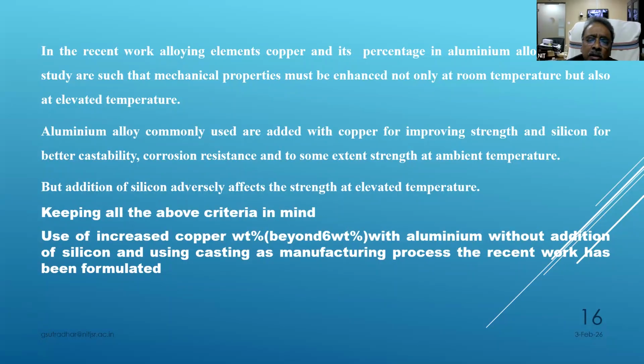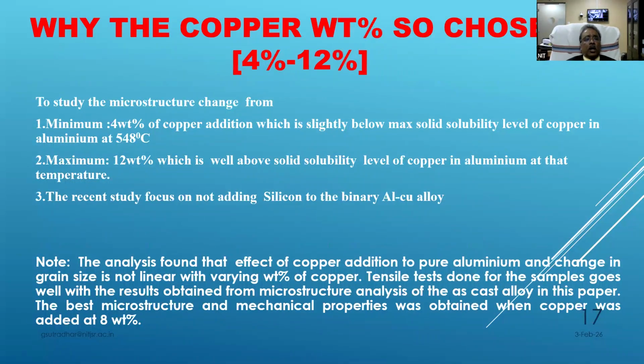We conditioned that we will go a little more than 6% weight of copper in aluminum, and without allowing any silicon, see how the material will behave, because silicon is basically not recommended for function conditions of at least 250 degrees centigrade or above. Now I will show why copper is chosen. In this experiment, we have taken three things, with minimum weight of copper addition in aluminum. I have said master alloy, and you go on adding aluminum and dilute.